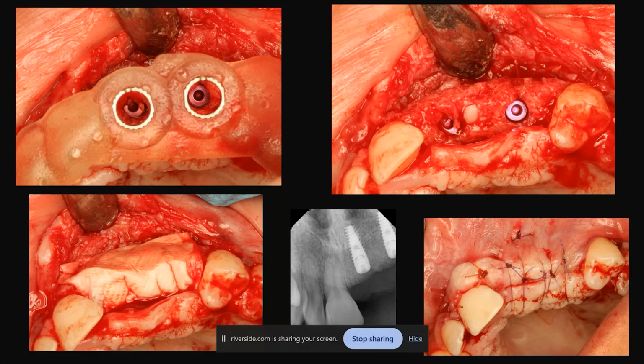Again, a cross-linked collagen membrane. This one's the Ossix Plus membrane. It's slightly different than the pericardial membrane, the Ossix Agile, but it is a cross-linked collagen membrane, not a native collagen membrane. It's cross-linked with ribose, which is a tissue-friendly way, it's essentially sugar, to link it together. That, again, just provides longevity and protection. It continues to allow the bone cells to keep cooking. And so I place my implants, place my membrane, and close it up again.